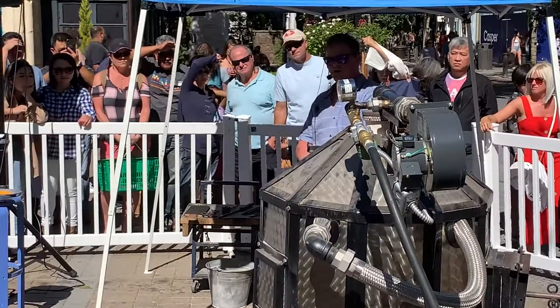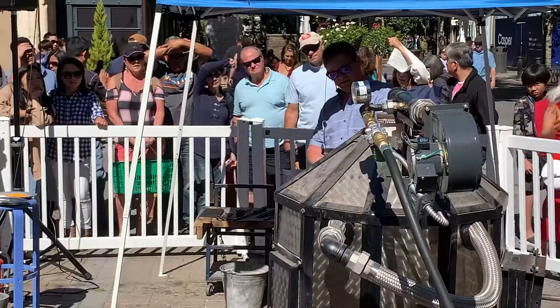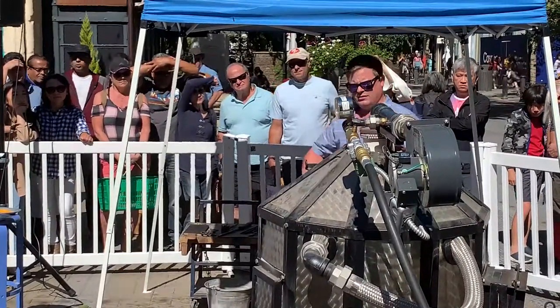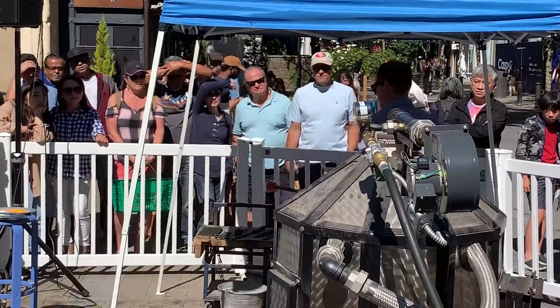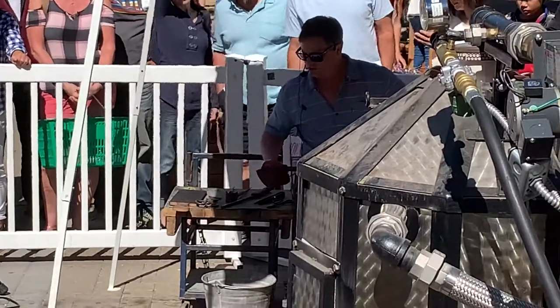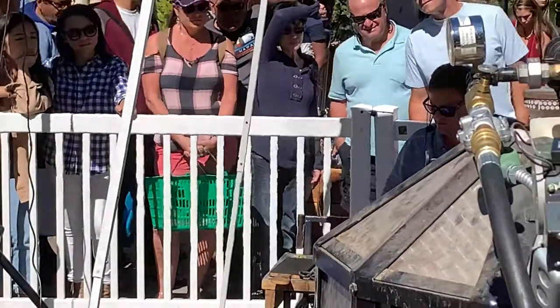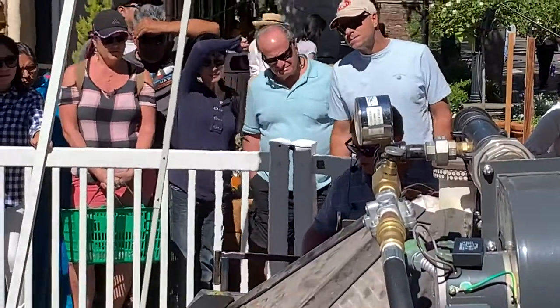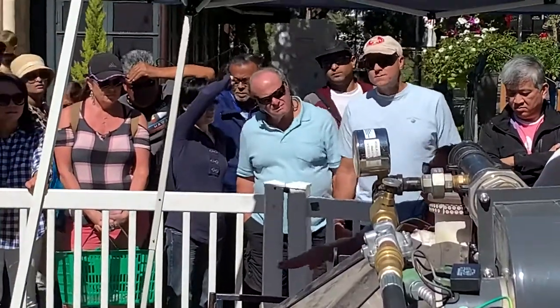In a traditional glassblowing shop we would have a secondary reheating chamber separate from the furnace, but for reasons of practicality I'm just using the furnace itself as a reheating chamber. Now that I've melted those little chips of glass into the surface of the clear, I'm going to use a handheld wooden mold which we refer to as a block to shape and smooth the glass — it's a process of symmetry. The block is made out of fruit wood which has never been allowed to dry out, and when we apply the block to the glass, the moisture evaporates immediately and the glass rides on a little bed of steam between the wood.